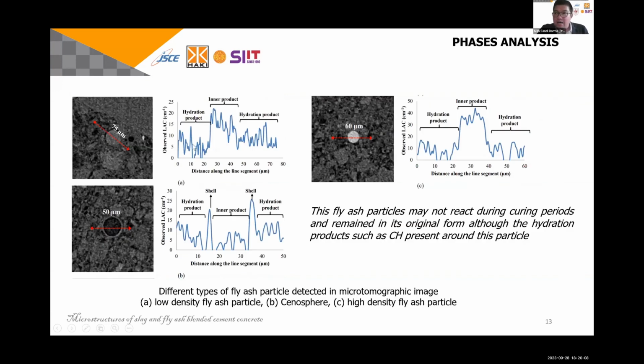And then the second, as several presenters said, by using the SEM, you can find the fly ash particle. In X-ray CT, you can differentiate several types of fly ash. Here we found a lower density fly ash, a high density fly ash, and finally a cenosphere, with high density in the outer and void in the inner. There are cenospheres as well as plerospheres in the fly ash. This cenosphere may contribute to high porosity in the fly ash sample.